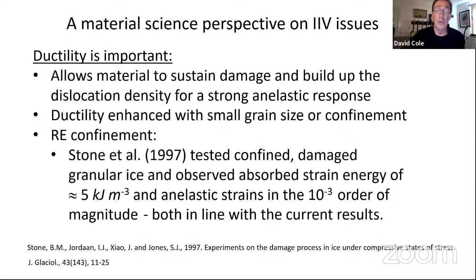Stone et al., there's some interesting work where they damaged ice under confinement, and Iliescu and Scholz, this is all detailed in the paper, did biaxial confinement on columnar freshwater ice, and both found that they could impart quite a bit more damage than you can in uniaxial experiments. The strain energy levels come out to be of an order of magnitude that is pretty much what we see, and the anelastic strains as well. So that's all very encouraging.